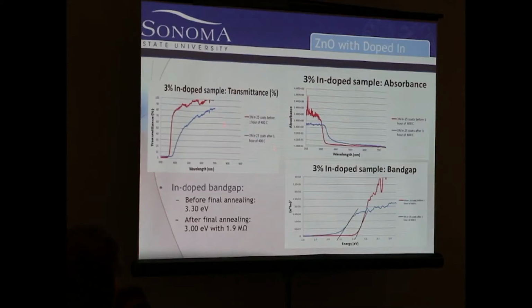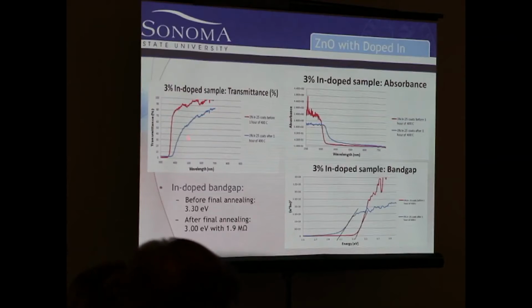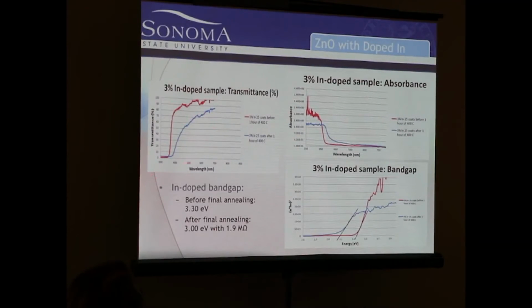So here, the blue line, after we annealed it for the big annealing, so that was really for an hour at 400 degrees Celsius, it really just helped bind the solution all together. So then we were able to get a resistance other than infinity, which I will show you soon. So this is a transparency plot, so you can also tell that the transparency of the red line is a lot nicer than the blue line, but we were able to see the change.